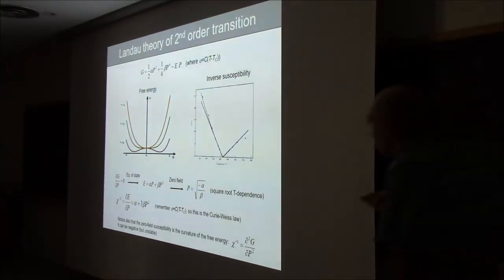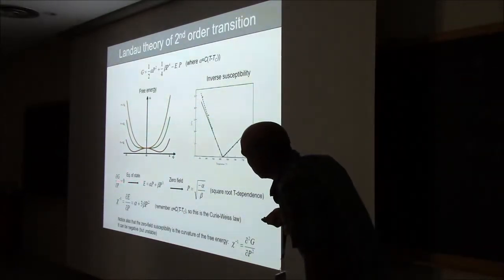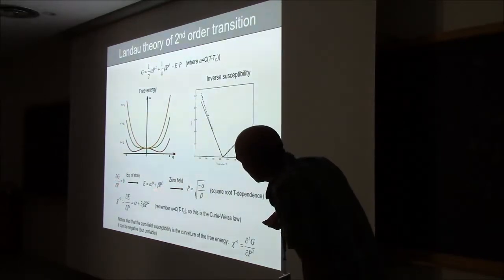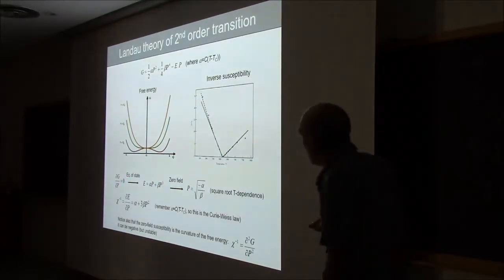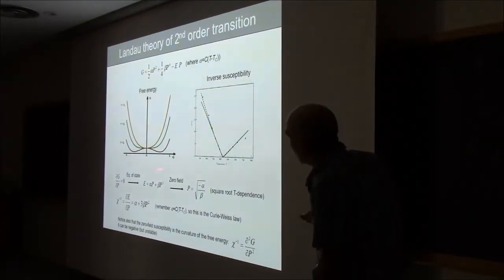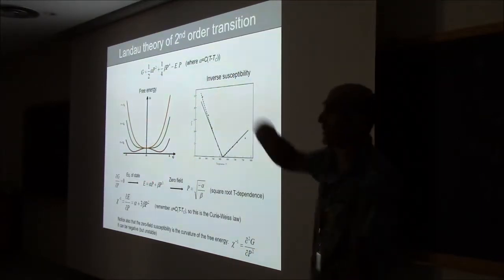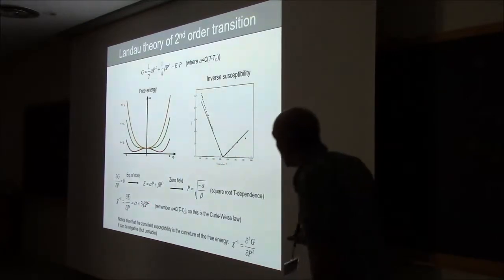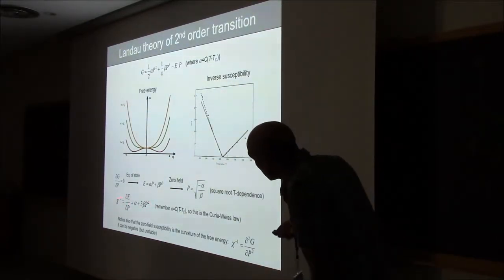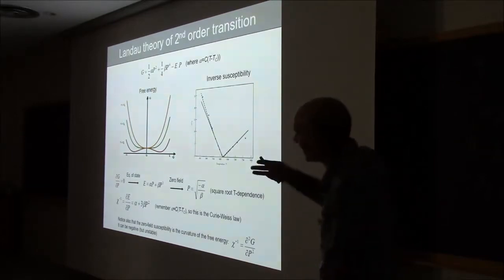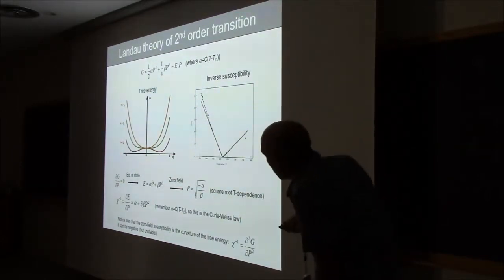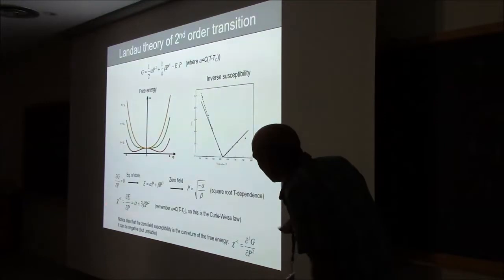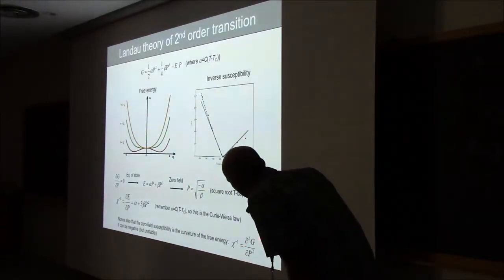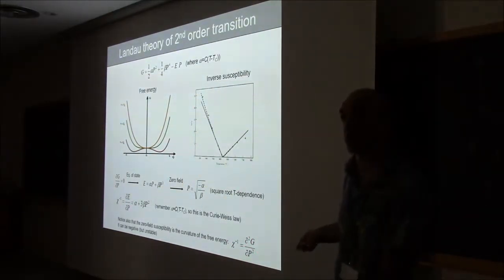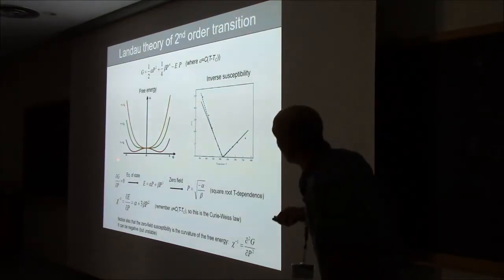One thing that is worth noticing: you get the equation of state by minimizing the free energy with respect to the polarization, which gives you this. The derivative of the electric field with respect to the polarization is the inverse susceptibility, which is this. You notice when you do this derivative, the electric field term basically disappears. This is another way to say that the inverse susceptibility is the same as the second derivative of the free energy with respect to the polarization, or if you want, the curvature of this.